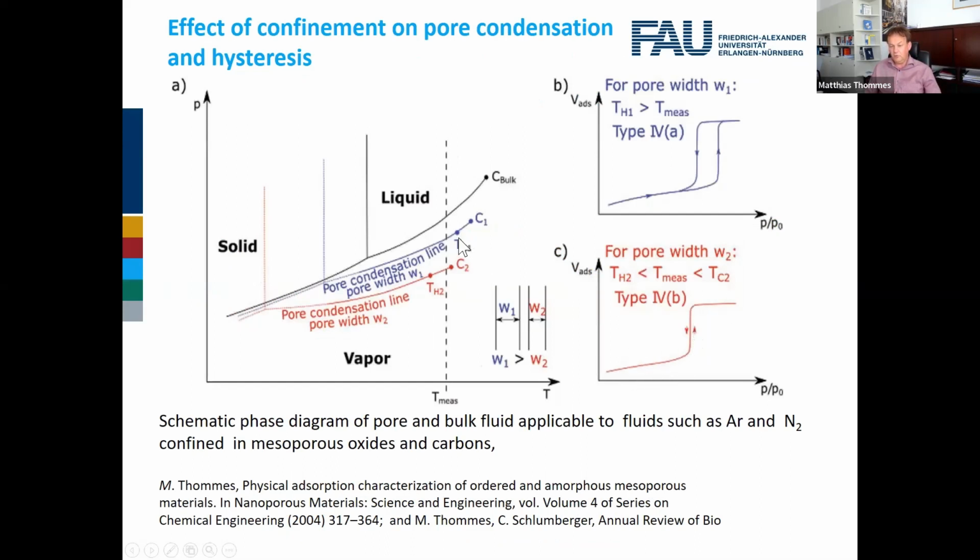Then, at the same temperature, for the larger pore, you're much further away from the critical point, and also below this hysteresis critical point, so hysteresis develops, and you have to overcome these nucleation barriers. This schematic diagram, strictly speaking, is only applicable to a slit pore, where you really have true criticality, both in the bulk and in the pores.